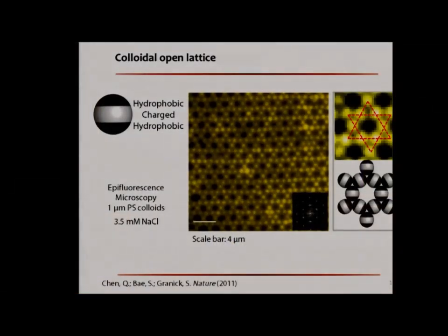They can form into a Kagome lattice. Really beyond the name, the significance is it's an open lattice. It's a lattice with large hexagonal pores. It's a lattice that is not closely packed. It's a lattice that a lot of people can think about when they relate to the traditional engineering of colloidal structures. You can see how ordered and crystalline the lattice is from the fast Fourier transform on the right corner.